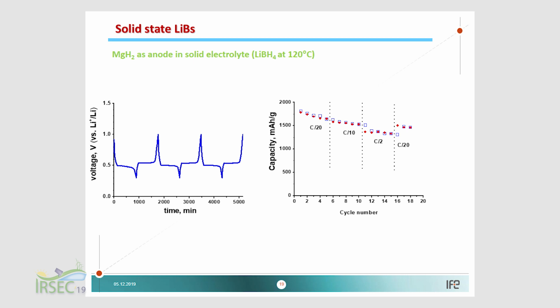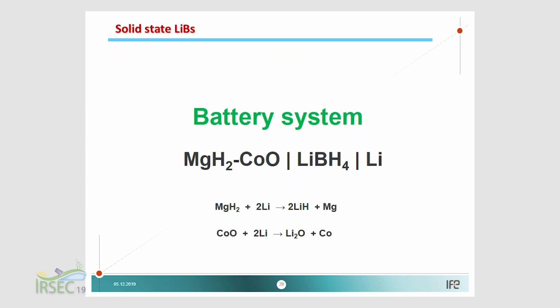And this is another presentation of this cycling. We could see this is really reproducible. And the people working, for example, with lithium iron phosphate could recognize that this is something really interesting, this plateau shape, and it can be reproduced. It's less than 5 years, let's say, since the discovery from the group of Professor Ishikawa of this work. So this needs to be reinforced, needs more research, of course, to be strengthened in this direction to use these materials as anodes.